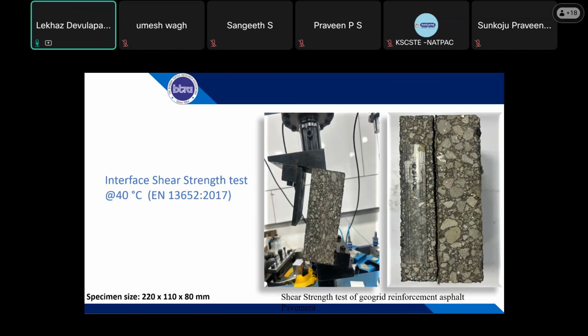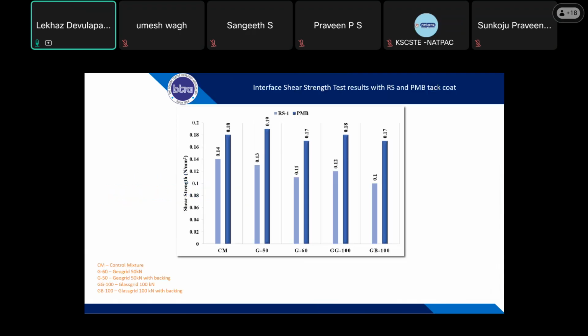And then we came up with the finding that 0.5 was giving okay results, and we fixed that tack coat dosage for these four geogrids. Then we did the interface shear test on these geogrids. If you see the control mix, without a geogrid, it was 0.14 with RS1 tack coat, and it was 0.18 Newton per mm square or MPa for the PMB tack coat.